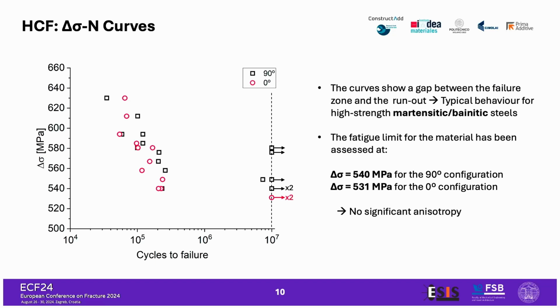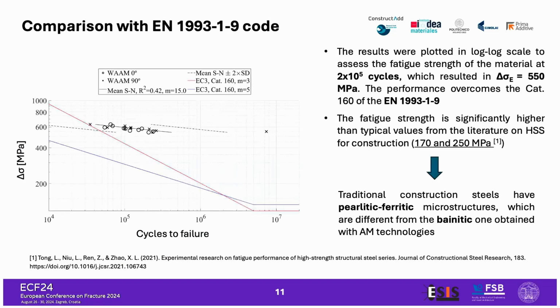Usually, it is typical to see fatigue properties in terms of fatigue limit at the runout. But since this material is being developed to be used for the construction sector, another thing that was important for us to assess was the fatigue strength at 2 by 10^5 cycles according to the Eurocode 1993-1-9. In this Eurocode, we have different categories assessing the fatigue properties of structures. And in particular, what you see plotted in the graph is the highest category for the Eurocode, which is the category 160 with the two different slopes 3 and 5.